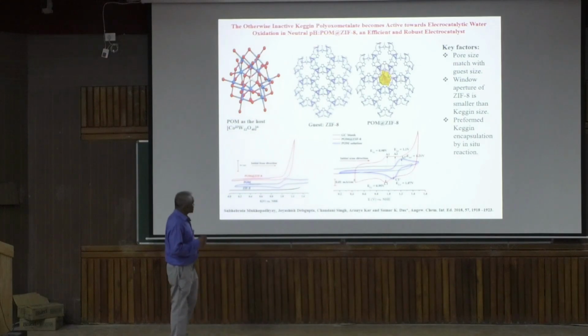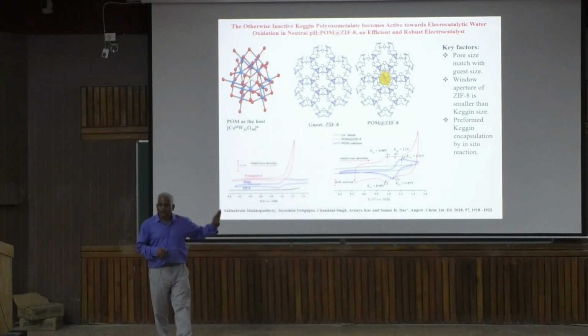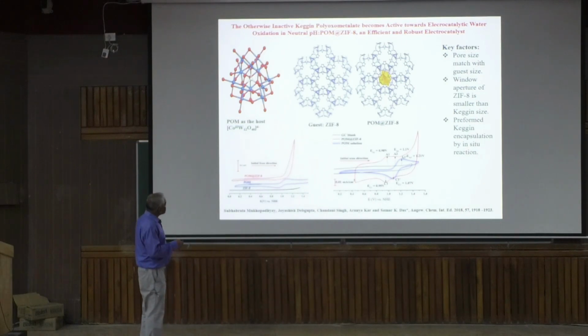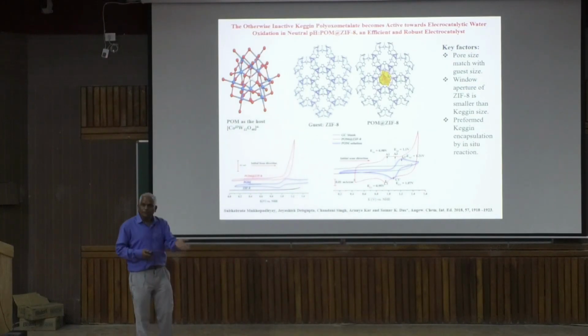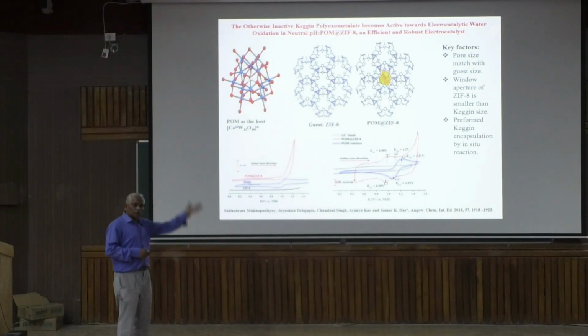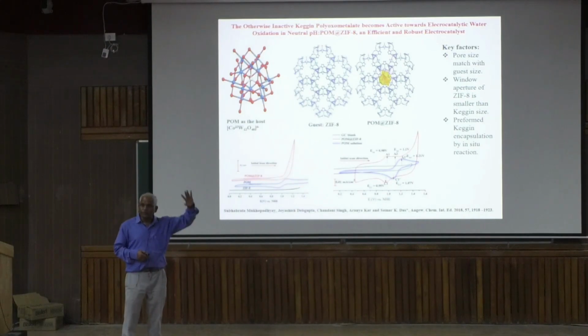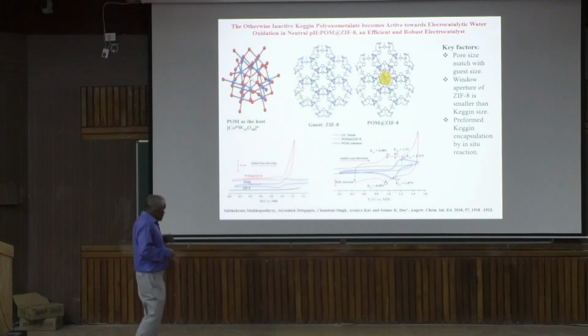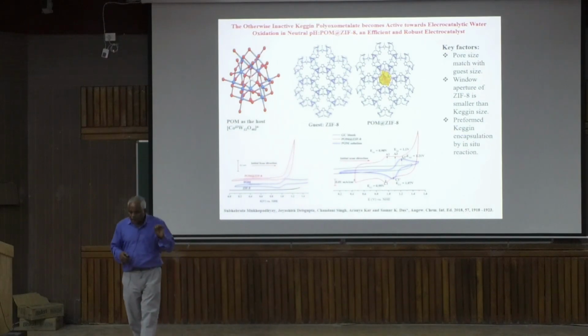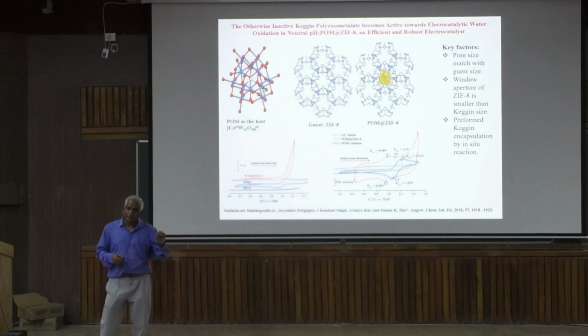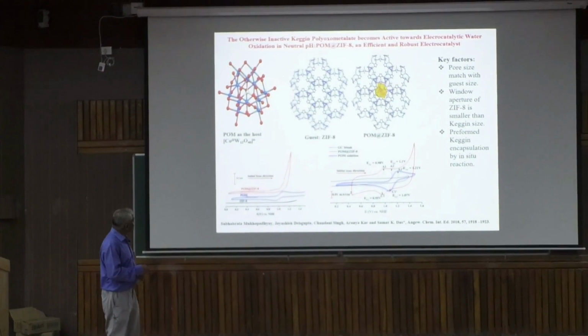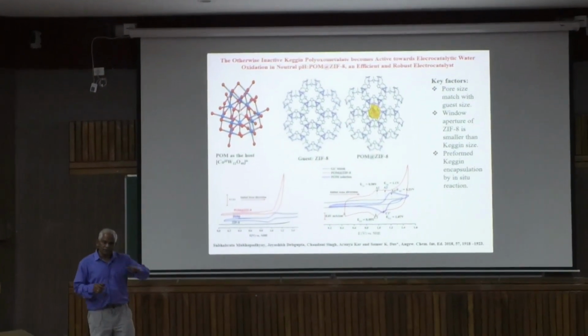Now, let me tell you interesting things. As such, the Keggin gives a 2-3 couple, cobalt 2-3, with no oxygen evolution. Once we put it inside, the feature completely changed. You see, whenever you get a huge current surge, that is oxygen bubbles coming, and we can say oxygen is formed. Not only that, this compound shows continuous oxygen bubbling for like 24 hours, and it works at neutral pH. Now I told you the Keggin compounds, polyoxometalates, generally decompose. In alkaline medium, definitely it will decompose. In neutral medium it may decompose, but because we encapsulated it, nothing happens. For 24 hours, you get oxygen.